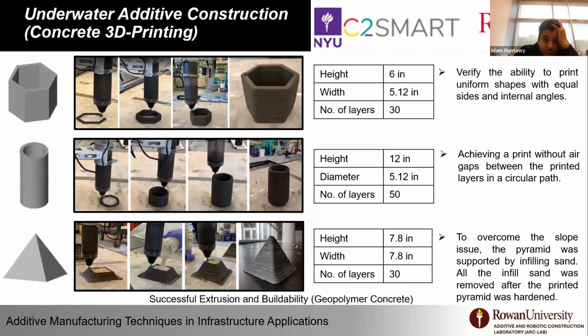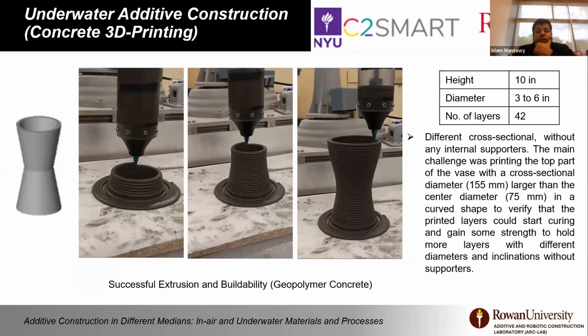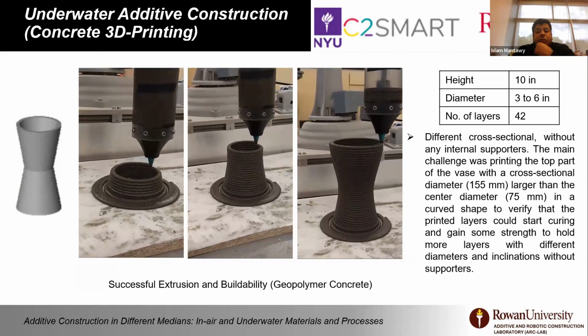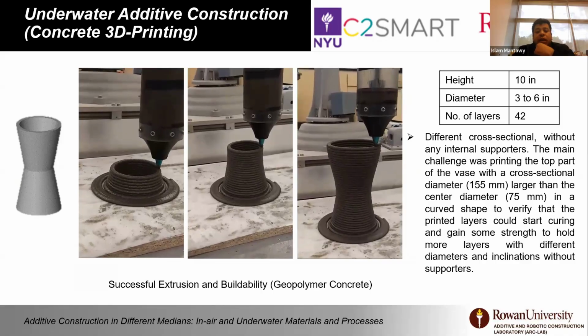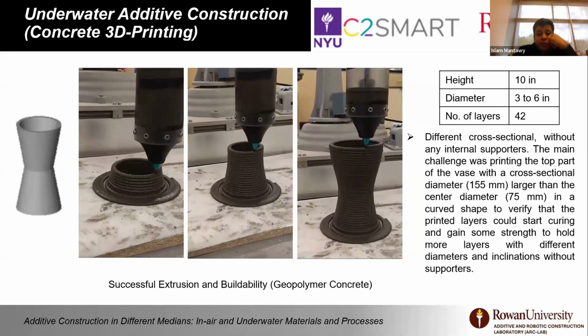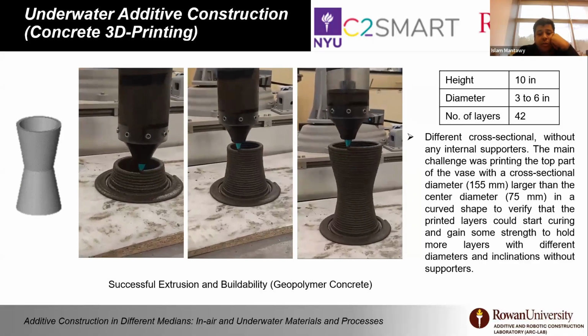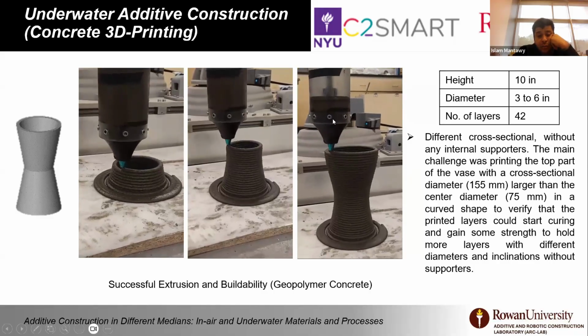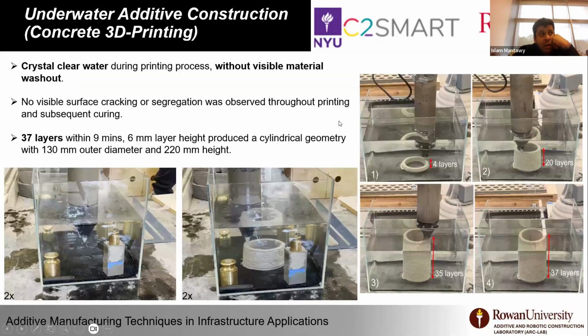So basically, we went through a smaller print from hexagonal to cylinder to sloped. The material doesn't have really great slope stability compared to what we developed in cementitious material. However, we were still able to achieve some slopes. Here is an example of a smaller print. Material open time, which is the time available for you to print, is very short compared to our cementitious material. So we need to conduct the process very fast.